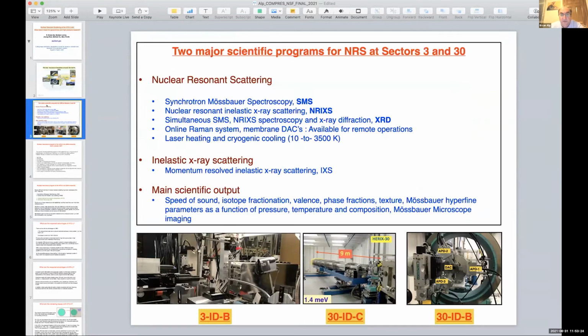So there are 2 major scientific programs for nuclear resonance scattering at sectors 3 and 30. The nuclear resonance scattering program is comprised of the synchrotron Mössbauer spectroscopy, which provides you hyperfine interaction information, and nuclear resonant inelastic X-ray scattering, which provides sound velocity and thermodynamic properties, where we conduct SMS and NRIXS simultaneously with X-ray diffraction.